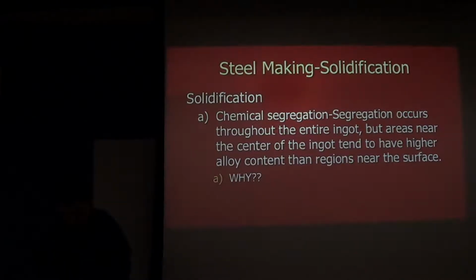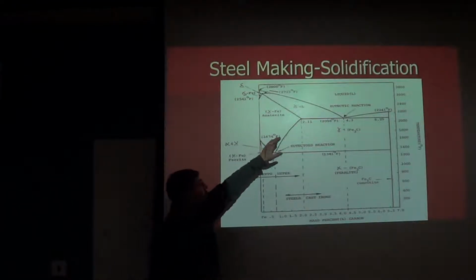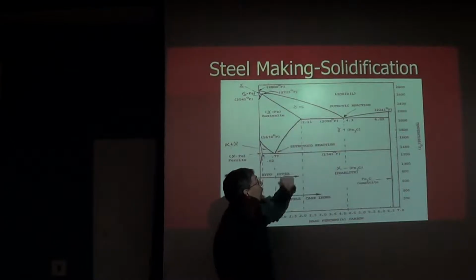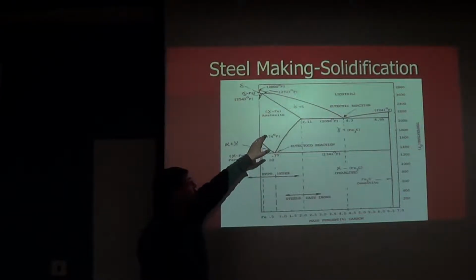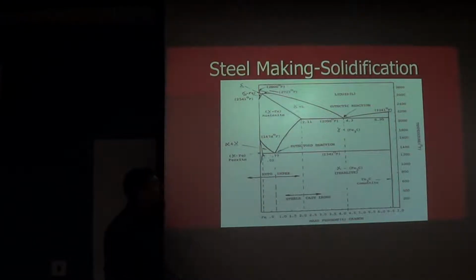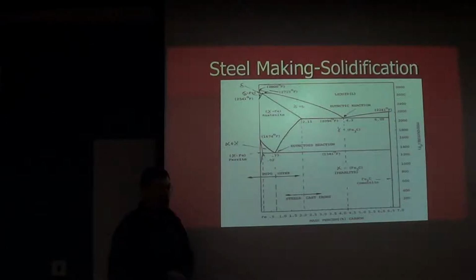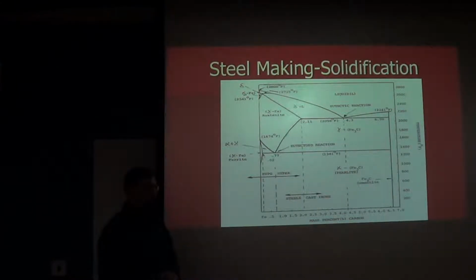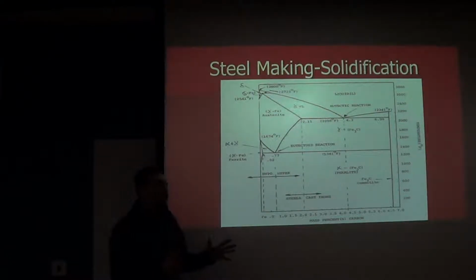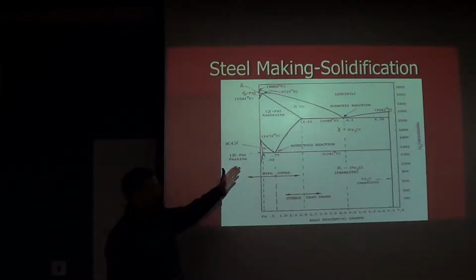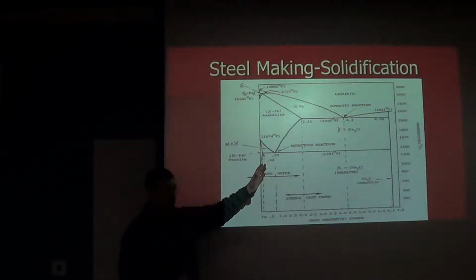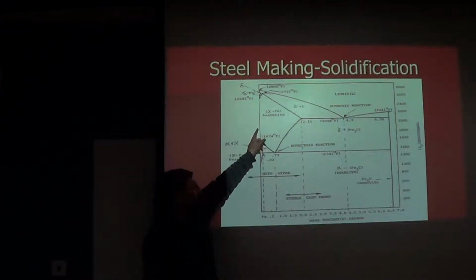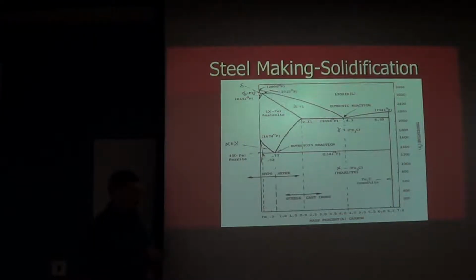Mm-hmm. Yep. So we can show what you guys both just answered by taking a look at our phase diagram. If we look up here, we have all liquid, and this is the liquid to solid line right there, right? And we can see with increasing carbon content, this line changes dramatically, right? So if you think about the metal that first hits that mold wall and is first to solidify, there's going to be a tendency to push carbon in particular away from that solid-liquid interface, right? And so that's what this diagram predicts. And the longer we are liquid, the higher the carbon content would be, because there's more time for that carbon to be pushed away from the interface.